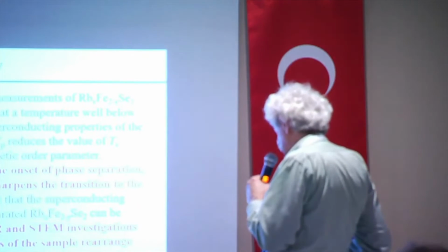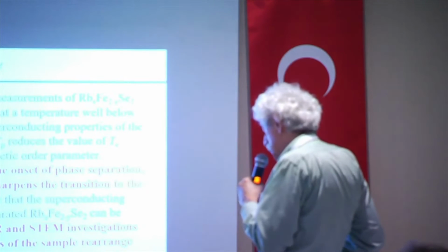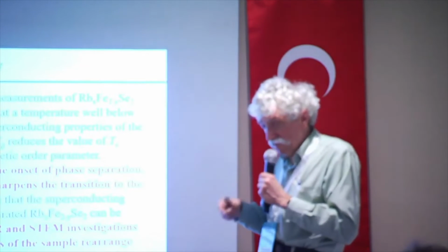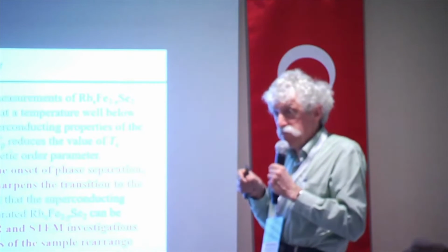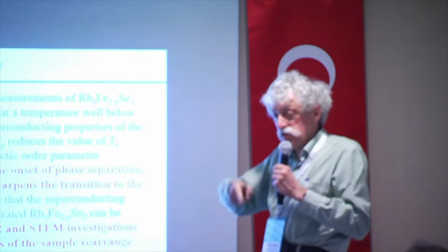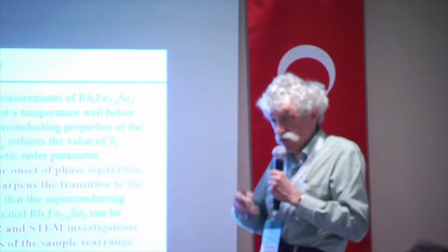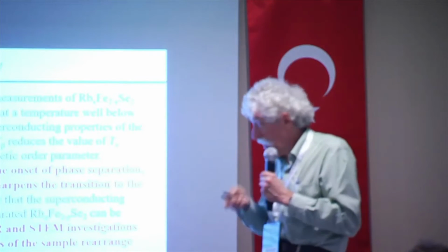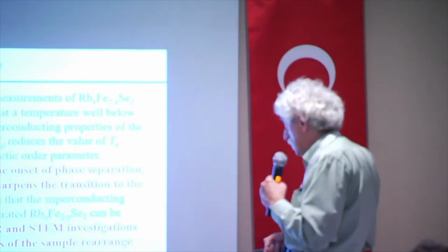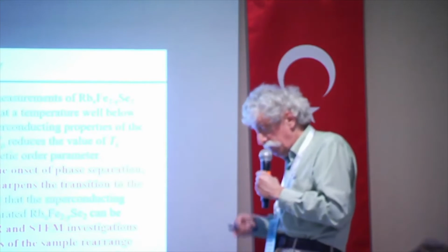as a result of annealing, there are non-magnetic regions in the sample arranged in this way, and as a result of annealing they became much smaller. The amount of them is identical, but they became much smaller, and because they became much smaller, you have much higher changes of magnetization in space, because the material is much more inhomogeneous. So again, we get the conclusion that bad structural properties mean bad superconducting properties, and good structure means very good superconducting state properties.